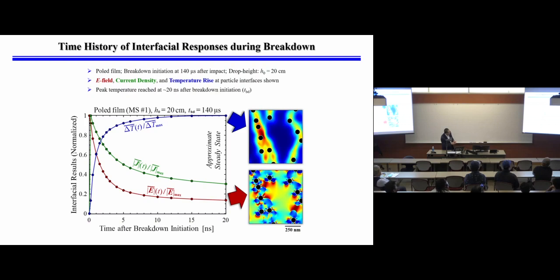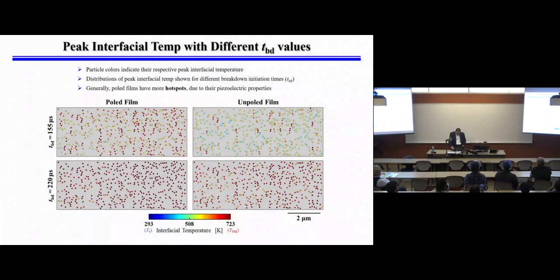the current initially is really high and then gradually decreases. The E field is very high and then gradually dissipates. And the temperature increases rapidly and then eventually reaches a plateau. And it all depends on how much electrical energy is stored in the material. We do systematic quantifications in the microstructure. The key is around the aluminum particles, because aluminum reacts with the polymer: what is the temperature increase? So we color each particle by the interfacial temperature, and we wanted to do statistical analysis.